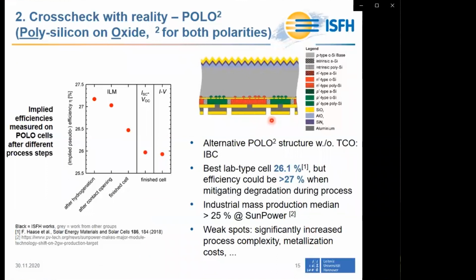However, you can also implement an electron collecting polysilicon oxide junction and a hole collecting polysilicon oxide junction in a cell concept without TCO if you put both junctions on the rear in an IBC structure. This is actually the cell concept for which we demonstrated the 26.1% on lab scale. And we think that this is not the full efficiency potential of this cell concept and this junction combination. The justification for this claim can be seen here, where we plot the implied pseudo-efficiencies calculated from injection level dependent infrared lifetime mapping measurements at different process steps. After passivation of our cell, the implied pseudo-efficiency is much higher than the final efficiency of the cell and exceeds 27%. The reason why we drop here is a degradation induced by the process. We are working on its mitigation, and we hopefully can achieve higher values in the near future.